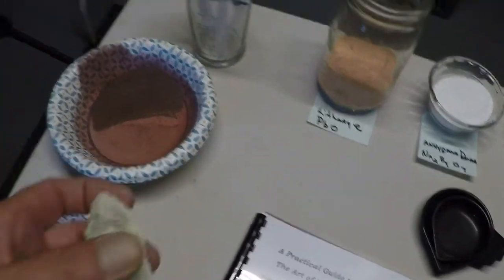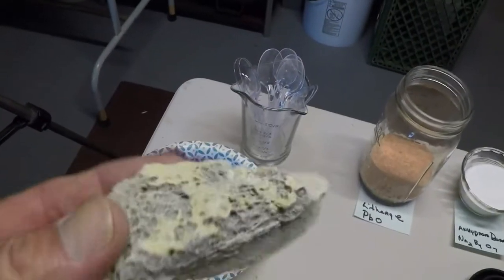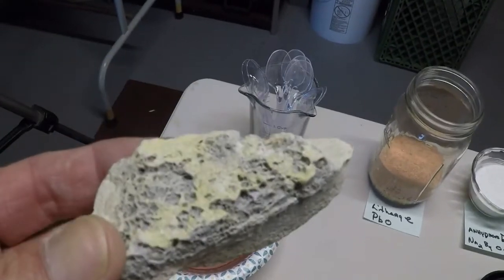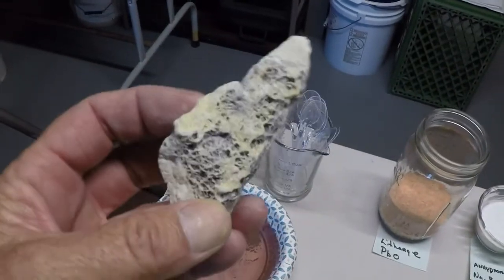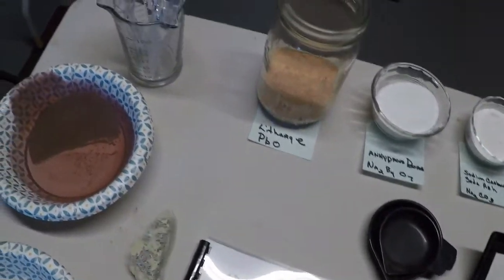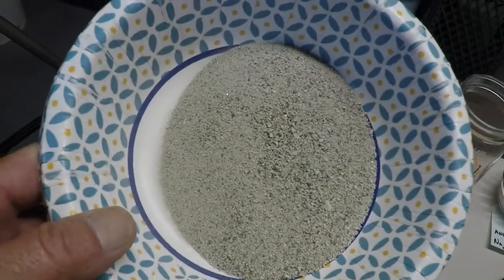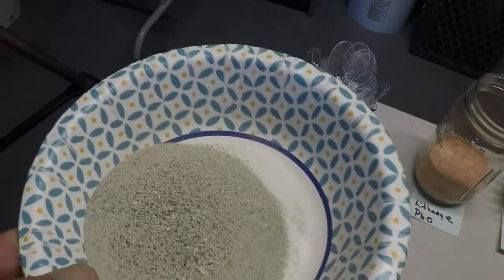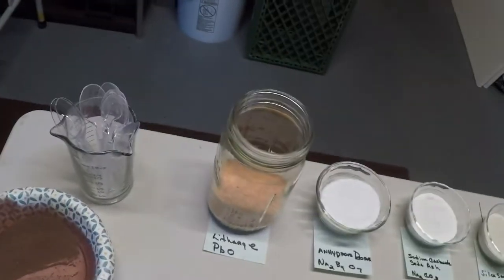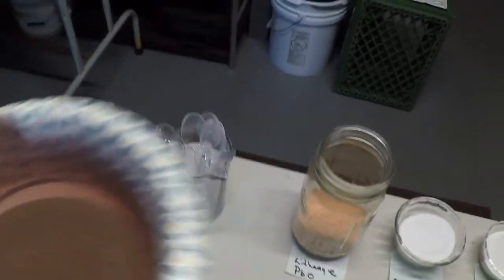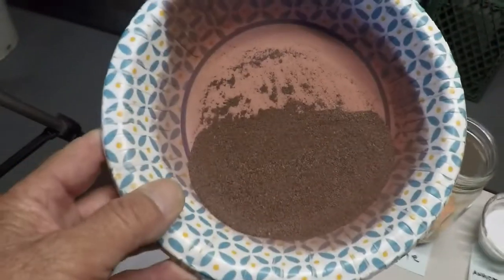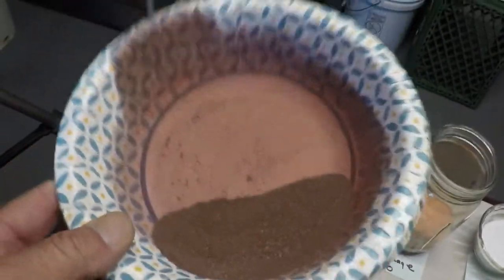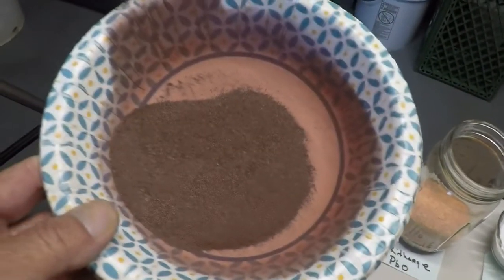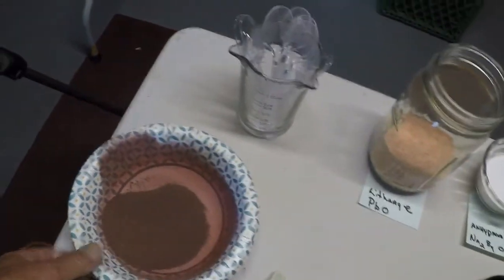Basically, we started with this rock that is a high-grade sulfide ore that's multiple ounces of gold per ton. We ran it through a crusher and then concentrated it with a little Miller table, and we got to this step, and then we roasted our ore. We reconcentrated again on the Miller table, a different process, and this is our ore after we've crushed it, concentrated, roasted it, and we're just ready to put it into the crucible to do a crucible fusion